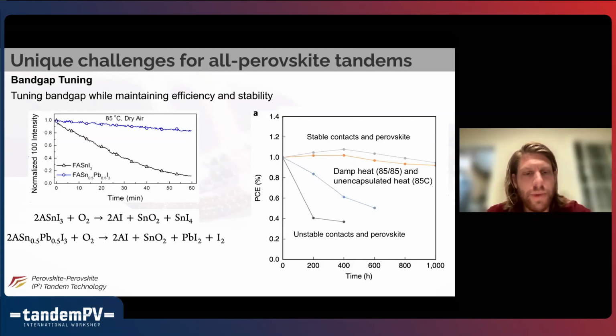The mechanism, in one case, for a pure tin perovskite, you form this SnI4, which has a low activation energy for formation and can leave as a gas very easily. If you have the tin-lead alloyed material set, then you actually need to break more metal halide bonds and do not form this SnI4, and the activation energy for that reaction is much higher.